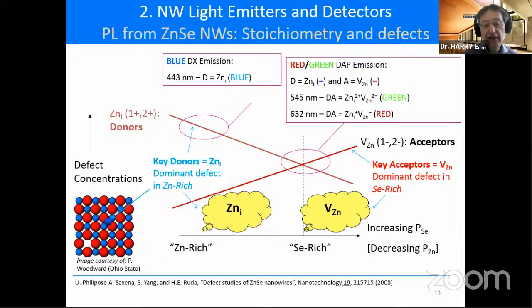On the other side of the diagram, and remember these lines, I didn't say, but the vertical axis when you do this Kroger-Vink analysis is actually a logarithmic scale. So these are exponential types of dependencies. On the right side, in the selenium-rich condition, you can see that there are comparable concentrations of both defects, and that's why donor-acceptor pair recombination comes into play on the right of the diagram.